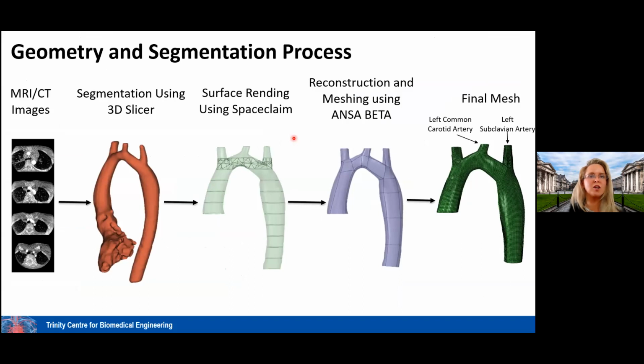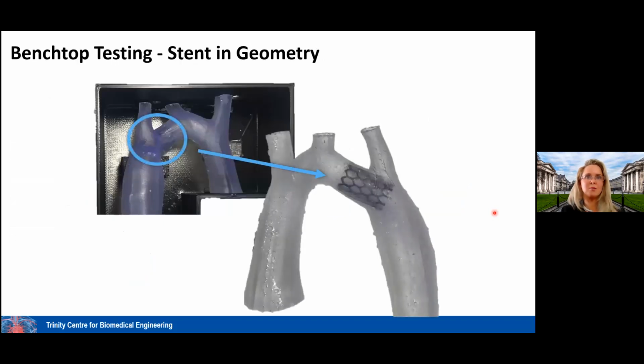Well, this is just showing you one example. As I said, we have other geometries also, but this is for that 5-year-old patient presenting. We were able to get a CT scan of that vessel where the stent was going to be placed up here in the coarctation. And using different software, we were able to create a mesh that we could use in that finite element software, to virtually simulate a stent being implanted into this particular vessel. What's also interesting is we're not just limited to creating that virtual model. We can also print that physical model using other printing techniques. So using stereolithography, which is a photo cross-linking technique, we can use an elastomer as shown here to print the vessel itself, keeping that patient geometry.